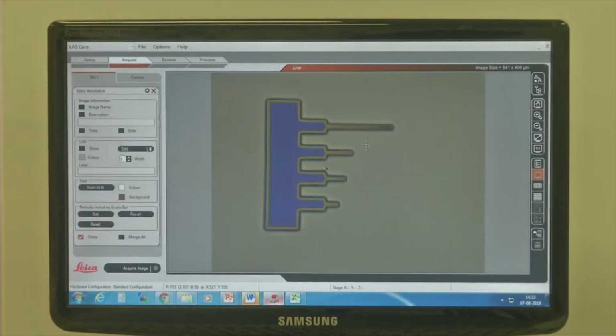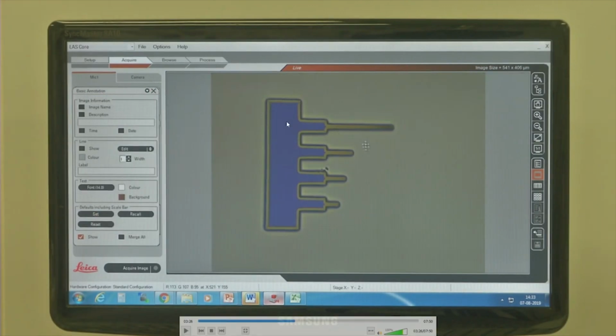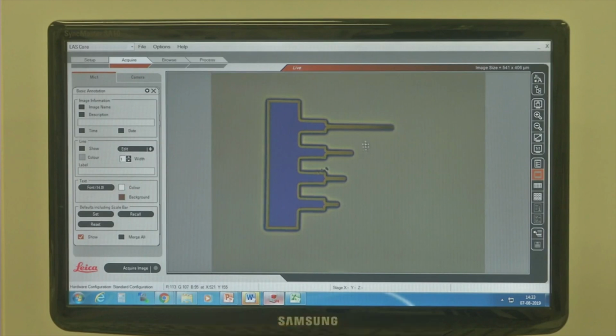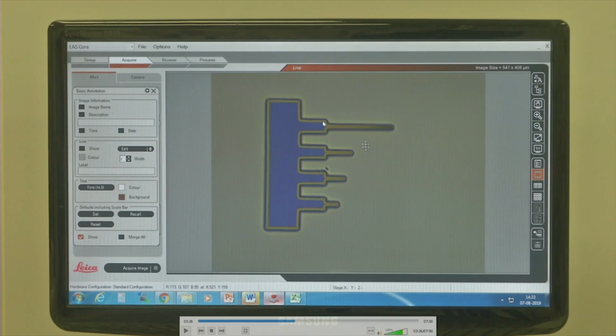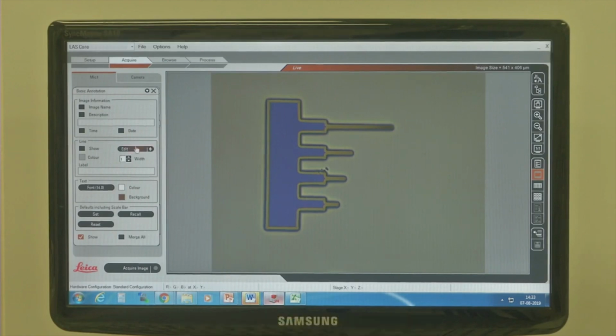What you see here is one of the cantilever groups. The blue is the tint that you get because you have silicon underneath. The whole region has silicon nitride. The blue region has silicon underneath, while this part has no silicon underneath. The light color that you see is nothing but the silicon nitride cantilever, and you can nicely see the isotropic edge feature looking sharp, right? If we zoom in, we can nicely see those features, and the inspection is done in order to measure the width and length of these features, which is very important during fabrication.